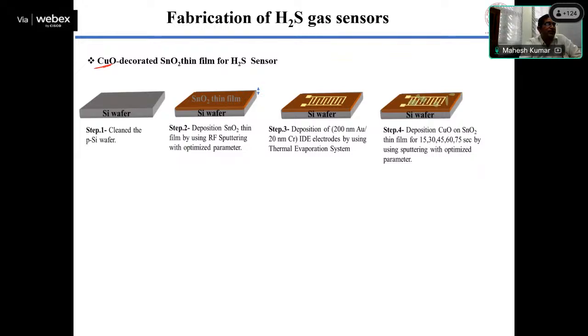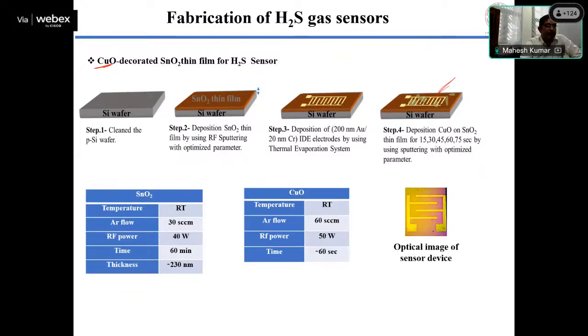Because of this, we have only decorated with copper oxide, but our main material is tin oxide. We deposit by sputtering. This is our device. You can see the deposition parameters here, and this is our sensing device. So we can take the contact from here and then do the measurement.